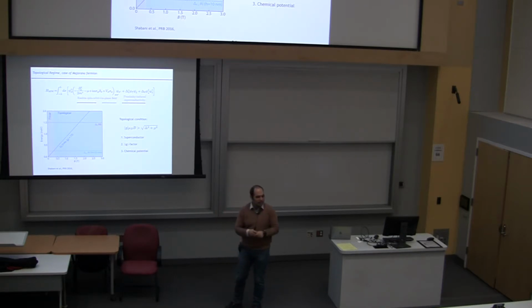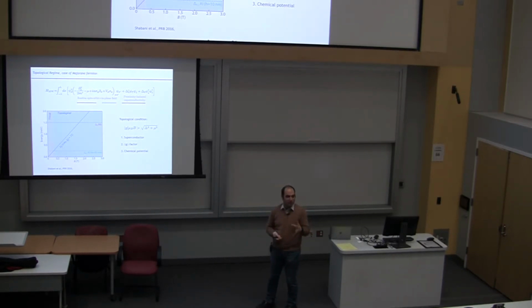But if you change your superconductor and say, I want to use niobium, then you go up. Now you are at 1.6 Tesla, right? The whole game changes. So the choice of material is very important. But this also tells you superconductors usually don't like magnetic field, right? Aluminum critical field is like 50 millitesla at most, and you're asking for 300-400 millitesla, so it's not going to work. Niobium is kind of the same. You want 2 Tesla, and niobium's critical field is probably around the same number. So when we want to design our material, we have to solve this problem. But let me go forward and tell you how we're going to attack this.